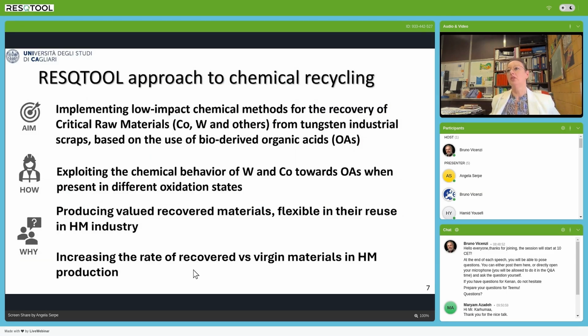This kind of approach has been used in the RESQTOOL project, trying to implement low-impact chemical methods for the recovery of critical raw materials from tungsten industrial scraps, in particular based on the use of bio-derived organic acid. The idea is to exploit the peculiar chemical behavior of tungsten and cobalt towards organic acids, which are present in different oxidation states in the material.